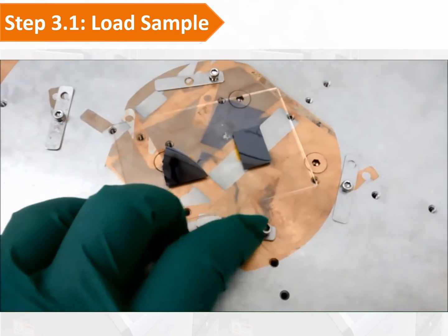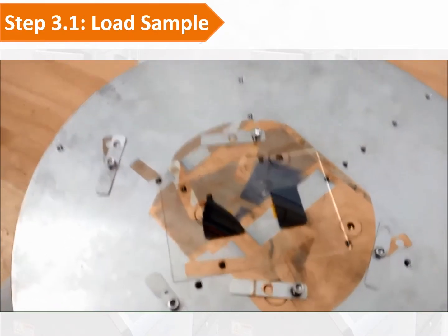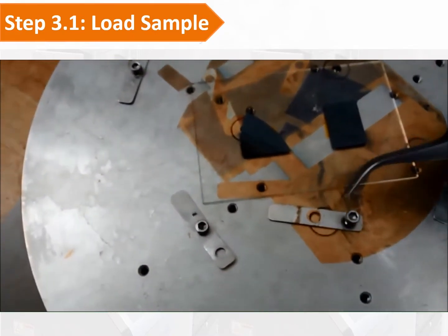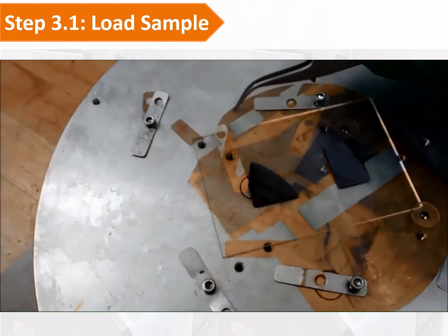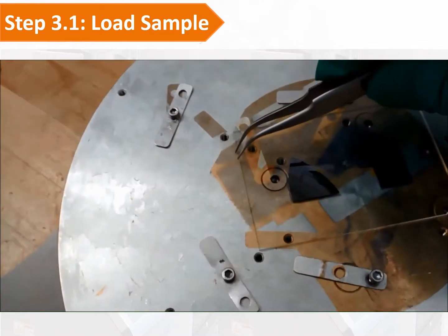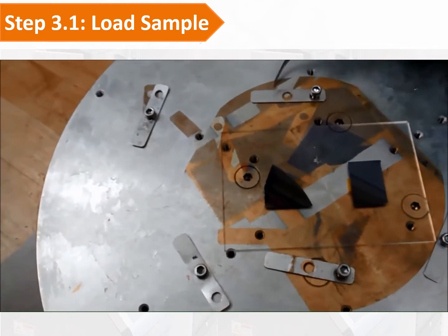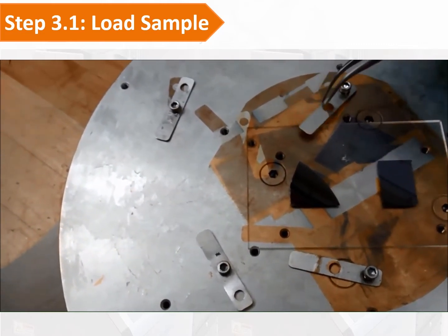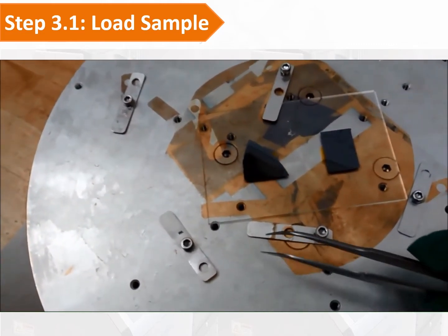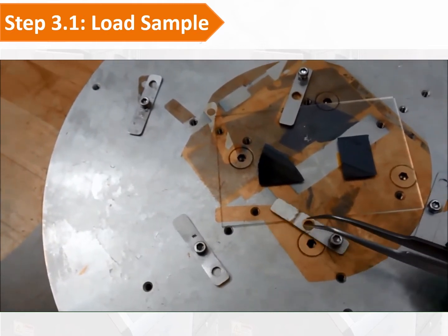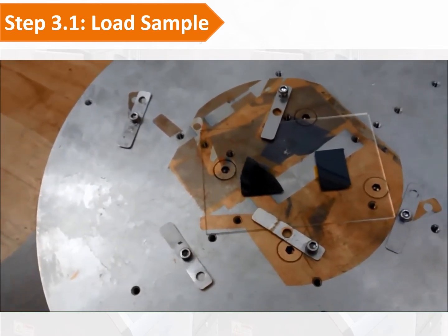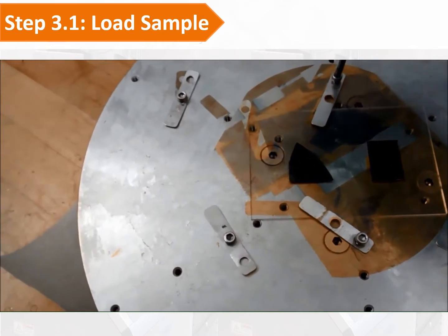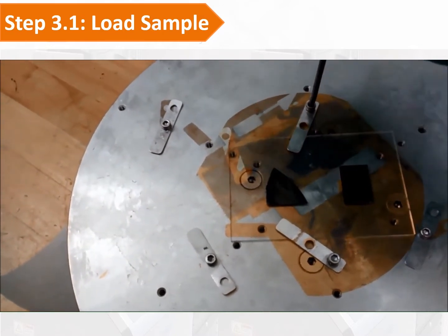You can move these metal clips to any position you want, but if you just have one sample, it's better to put the sample in the middle of the sample holder. It will give you a more uniform coating on top of your sample surface. And then we put the metal clip on top of the glass slide, and then we just tighten those screws.